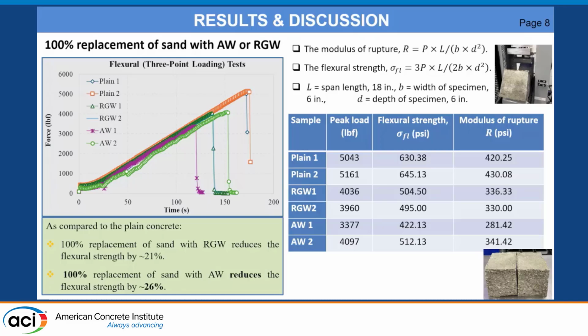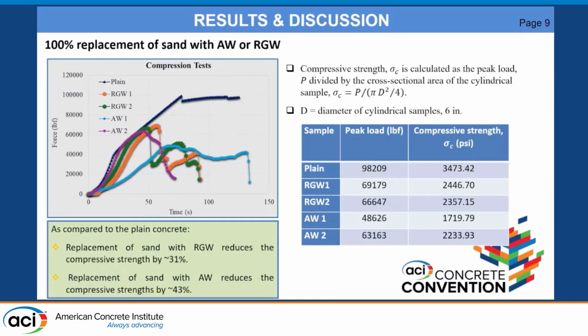So they're very busy over there at Alfred University. They have a lot going on, and a lot of their stuff is very cutting edge. So they did the best they could to supply us with stuff. But again, with the recycled glass, we see about a 21% reduction in flexural strength, and alumina waste about 26% for a 100% replacement.